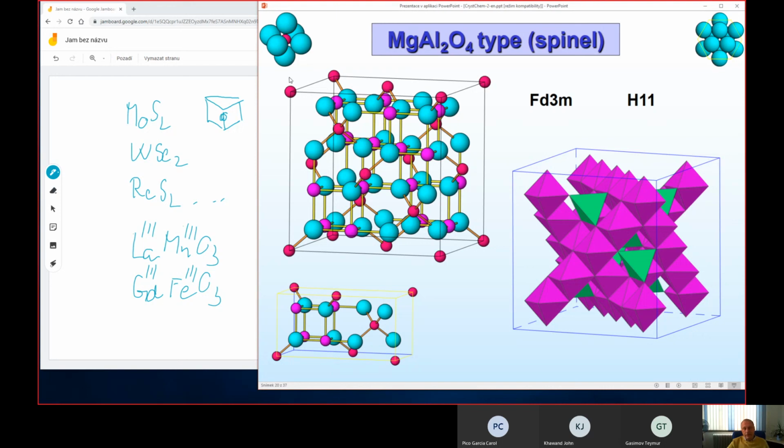If you look at this unit cell, where the atoms in tetrahedral positions are in the corners, it is a cubic unit cell with Fd-3m symmetry. So if we place the atoms in the corners, then you see that there are additional atoms here and here, and here and here, which corresponds to a diamond lattice. This is a diamond lattice of atoms which occupy the tetrahedral sites.